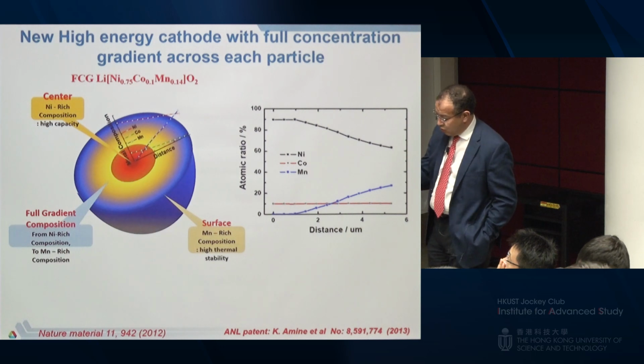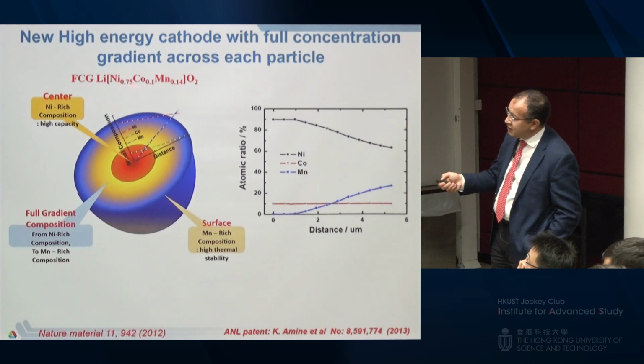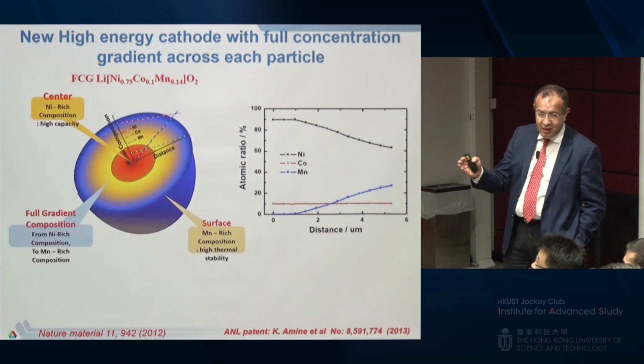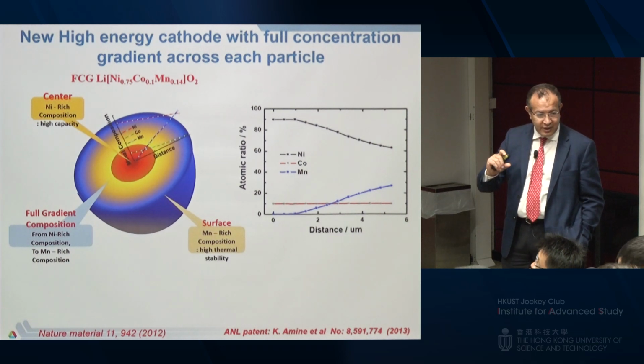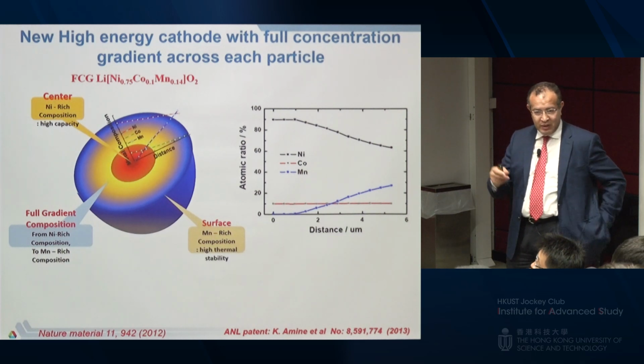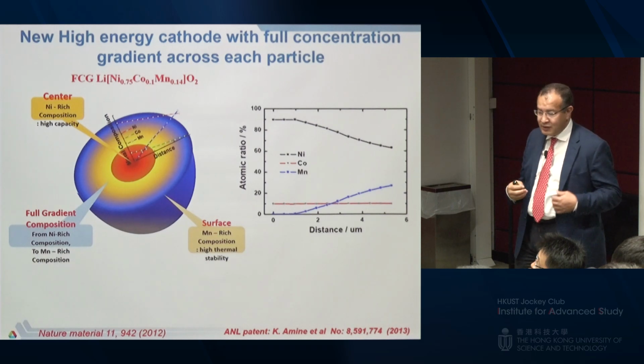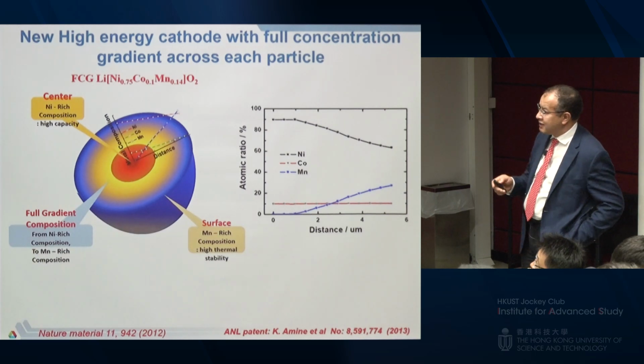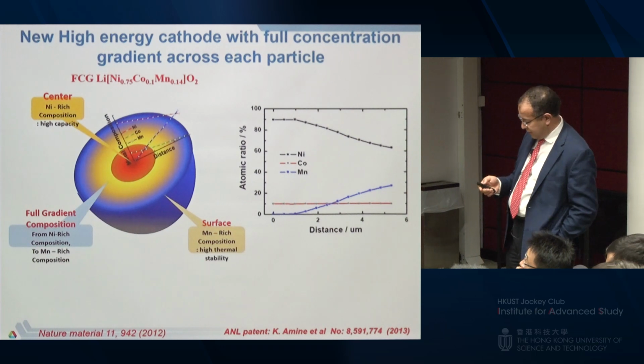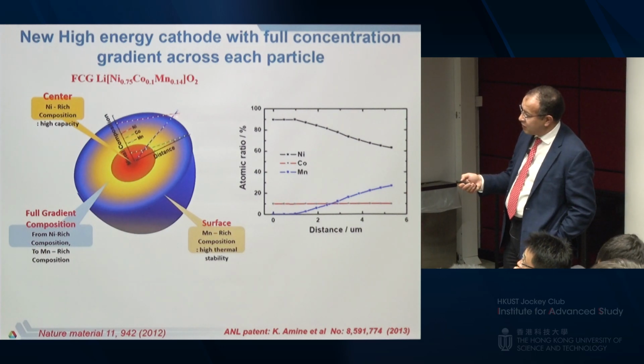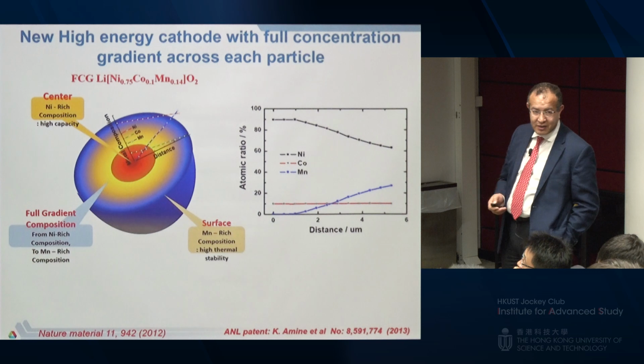And the reason why we go slowly is because there are volume changes. If you make a big composition change quickly, you create a gap in volume, and then you have a kind of separation. So you have to be careful about that. That's the reason why we did a full gradient. The full gradient will allow you to put in as much manganese as you want, depending on the particle size.